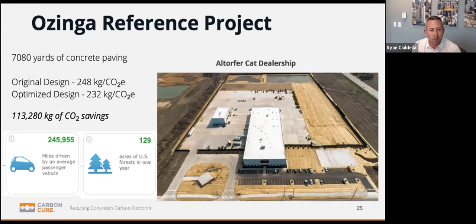And then just some rough figures in terms of what that does. It's about 129 acres of forest absorbing CO2 for a year, and about 250,000 miles driven by the average passenger vehicle. So as you can see, just the incorporation of CO2 and allowing for that cement reduction, you can have a pretty big impact. And, again, as Allison mentioned, it's not just the incorporation of that 1 pound of CO2, it's really the cement reduction where the value really occurs and where you start to see some of the savings.